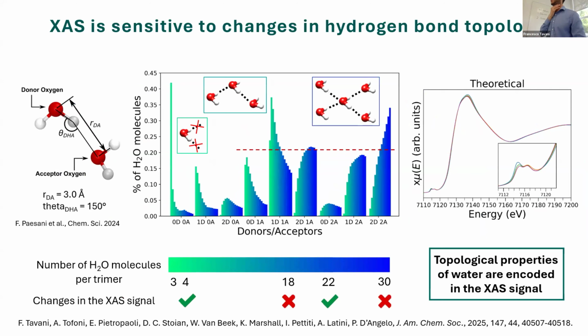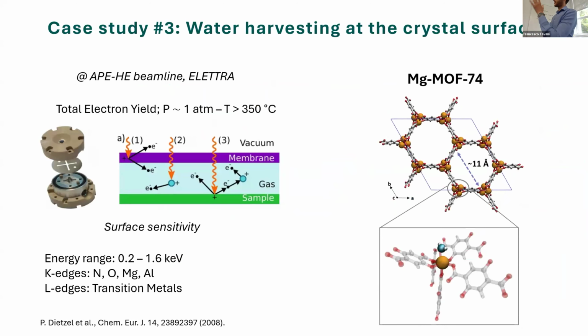So this was basically the main conclusion of this work. And as a last case study, I still have some time, so I just wanted to briefly tell you about how these techniques can be used to investigate surface effects. As I mentioned earlier, if we change the energy of the XAS probe and turn to soft X-rays, so here I'm talking about energies from approximately 0.2 to 1.6 keV, we are intrinsically diminishing the penetration depth of the X-ray probe due to the lower energies. And the way the soft X-ray beamlines are built, the detection techniques are at an increasingly surface sensitive layer. What do I mean?